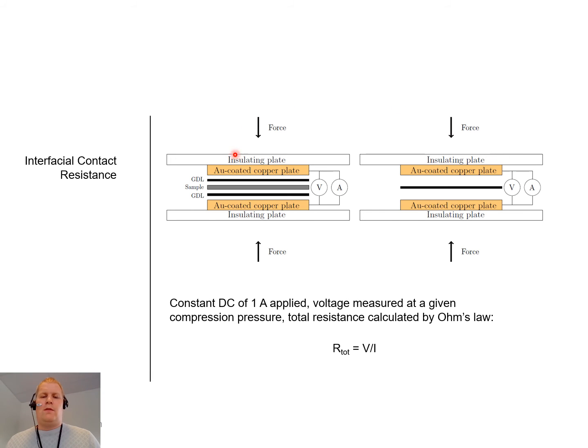Here's an overview of the device that we use to measure the interfacial contact resistance. You place the sample between 2 GDLs and then you sandwich them between 2 gold-coated copper plates. You apply a force and then you supply a constant current, which in our case was 1 amp. Then you measure the voltage with a voltmeter. Then you also do this for only 1 GDL sheet.